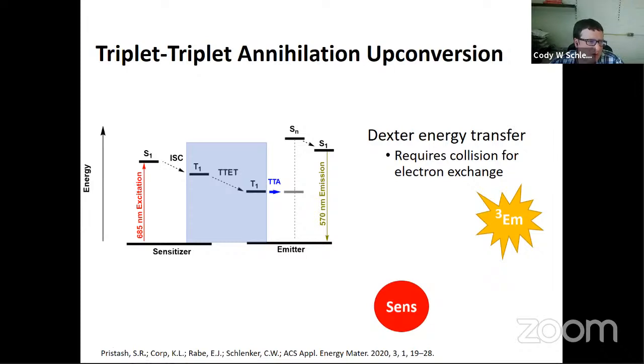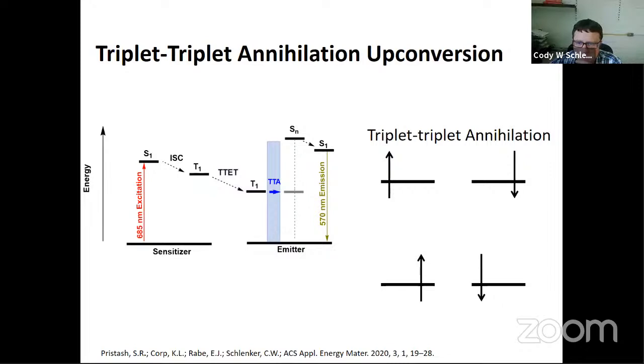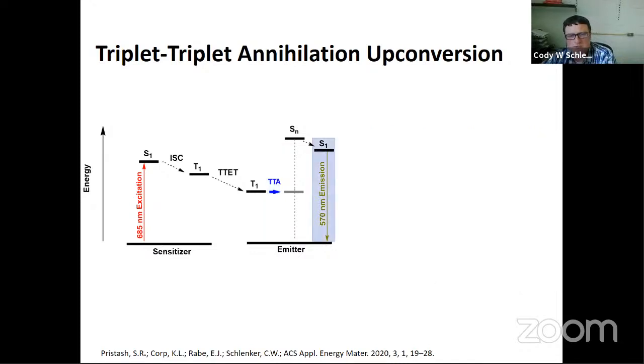a spin conserved process that takes 2 triplets and fuses their energy into one singlet state, in an overall spin conserved process that is more or less summarized here, where you have electron exchange between 2 triplet excited states, and it overall forms a spin singlet excited state and a spin singlet ground state. So you have this process of annihilating 2 triplets and generating one singlet.